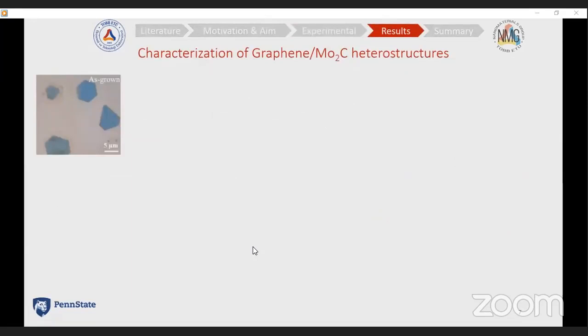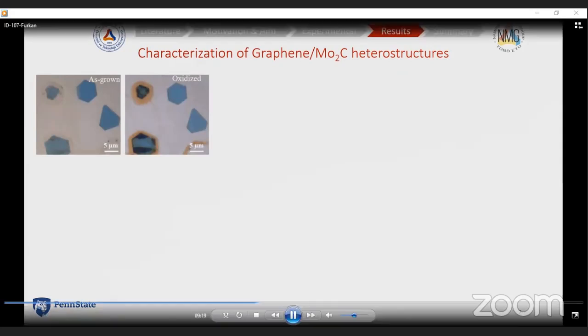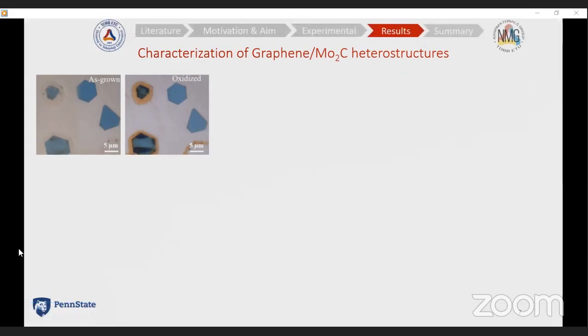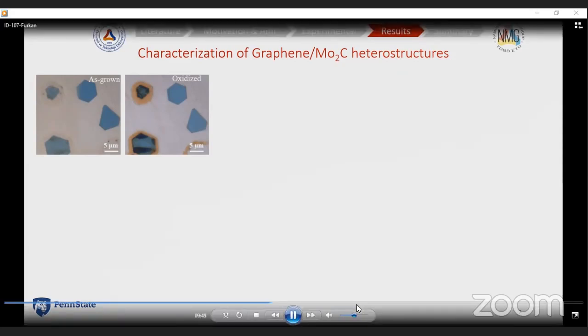So this is an optical microscope image of the as-grown sample, and this one was taken after the oxidation of the sample at 200 degrees C for 5 minutes. And this oxidation was done to see the graphene coverage on the copper surface, because in the absence of graphene, the copper was expected to oxidize, while the graphene covered regions were protected from the oxidation. So this orange color represents the oxidized copper, while the blue color is the graphene covered regions. So it is actually observable that 2 different crystals are formed under these conditions. One of them is molybdenum carbide on copper, the other is molybdenum carbide on graphene.